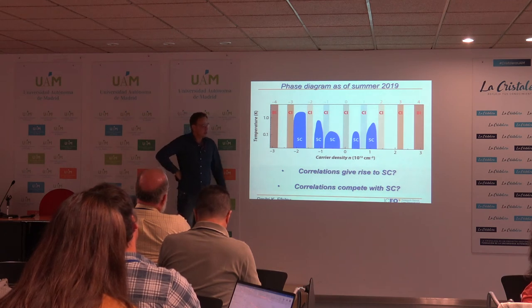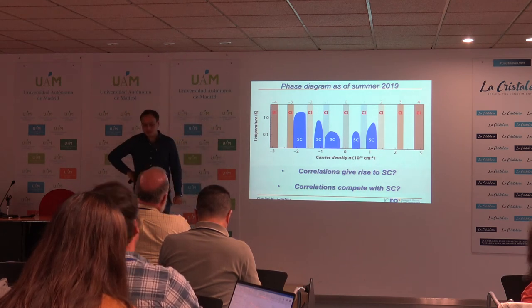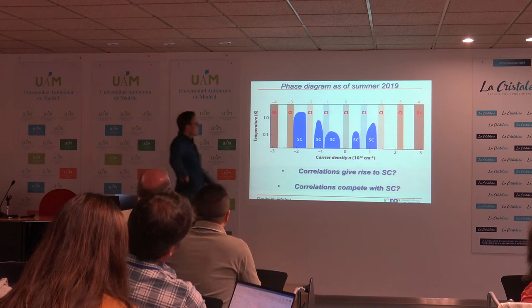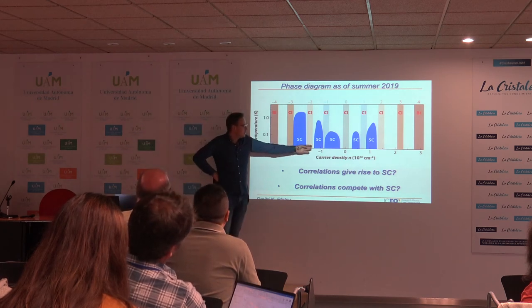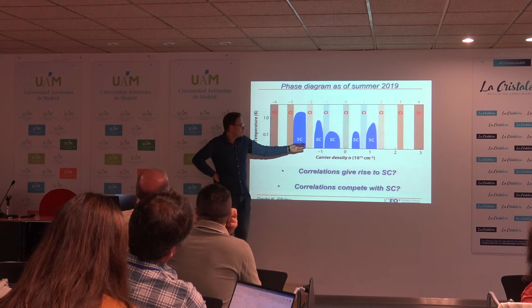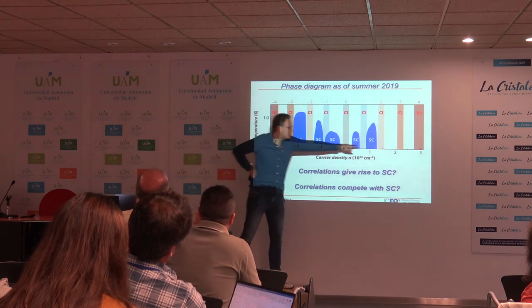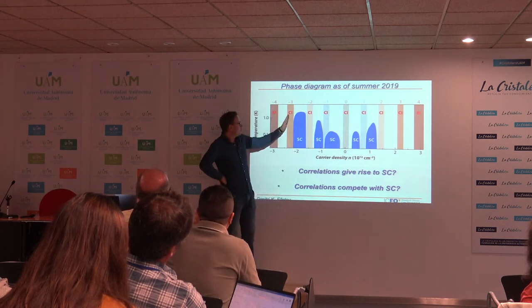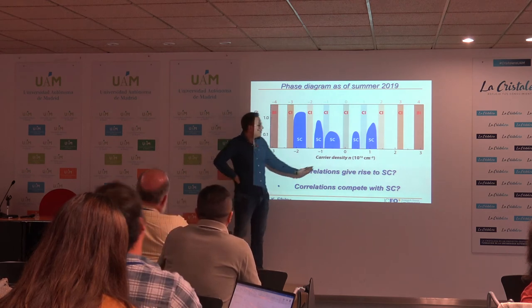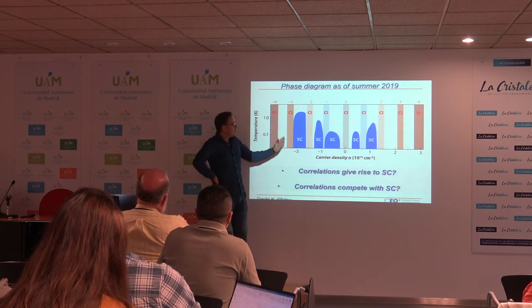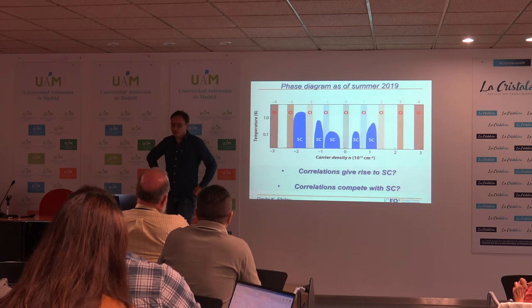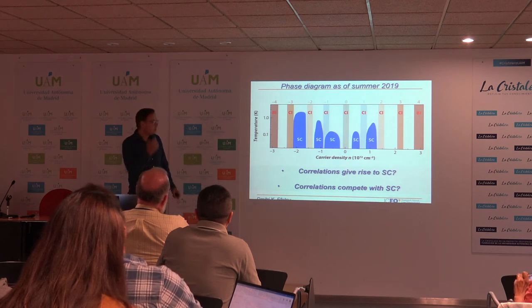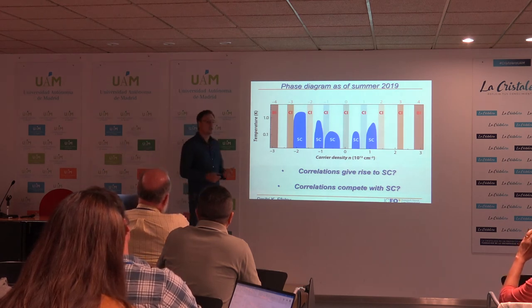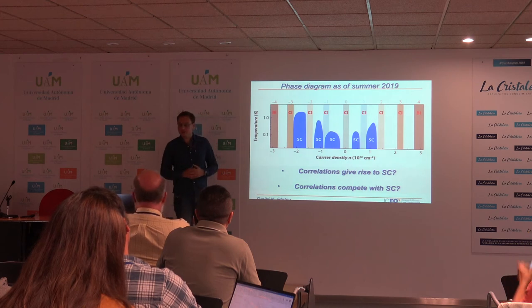So in principle, the evolving picture now is the following: not just at half filling do you have these correlated insulating states flanked by superconductors. This appears here and here, but we also have many more correlated insulating states which can appear at all the integer fillings of the system. And then, around these correlated insulating states in many locations, you can find dome-shaped superconductors which are flanking these. And of course, you could start thinking along different lines.